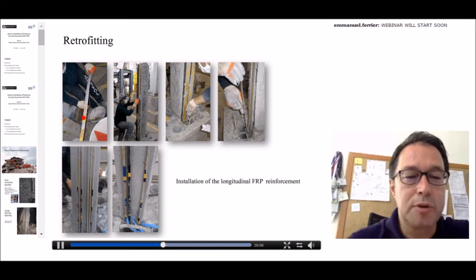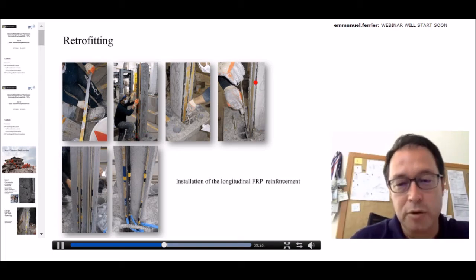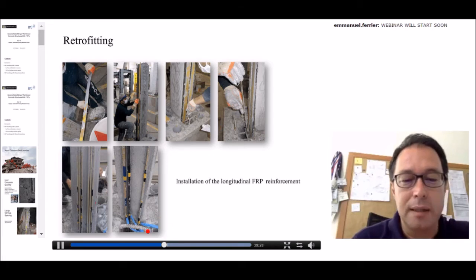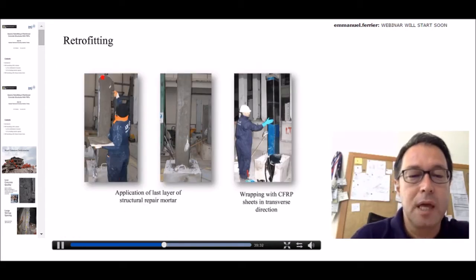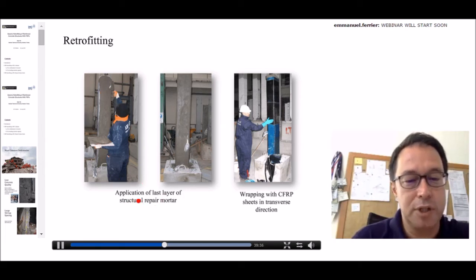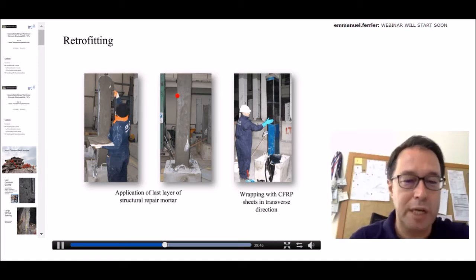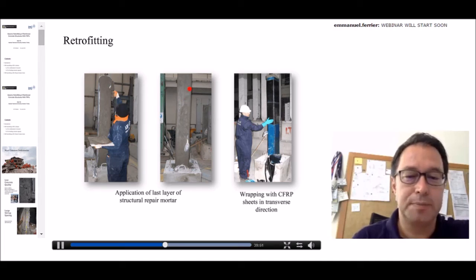And what we do is we use epoxy to bond either the laminates or rods. You see the rods here, laminates here, to bond them on the surface. But the surface is now a better quality surface. It's a high strength cement-based repair mortar, not poor quality concrete, and that's very close to the main reinforcing bars. And we use the last layer of structural repair mortar, which is again a much better quality than the original concrete. Now the geometry of the column is equal to the initial geometry. So again, we don't change the geometry. All the intervention has been done within its original dimensions.